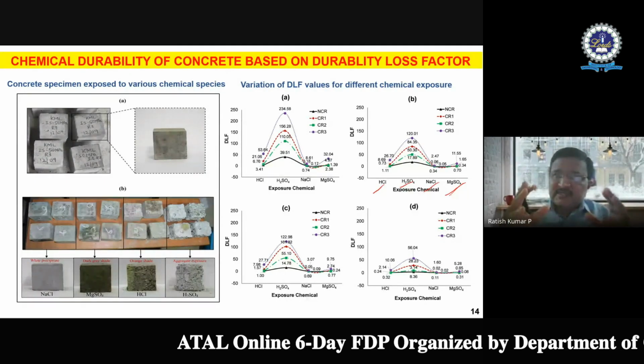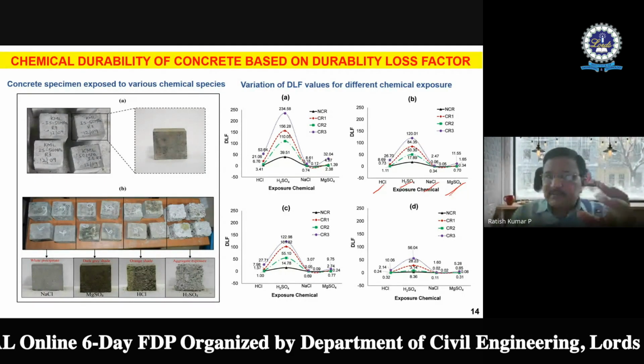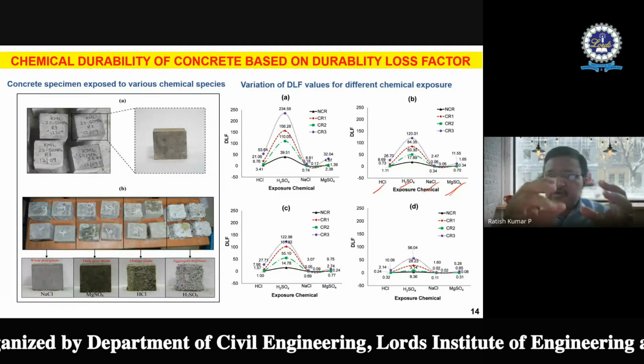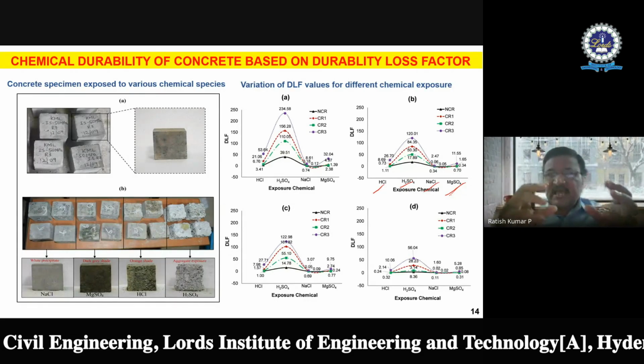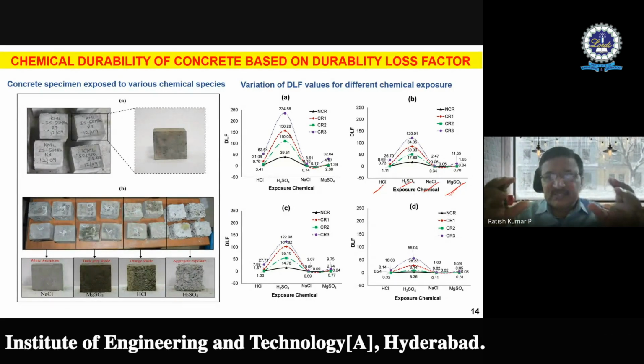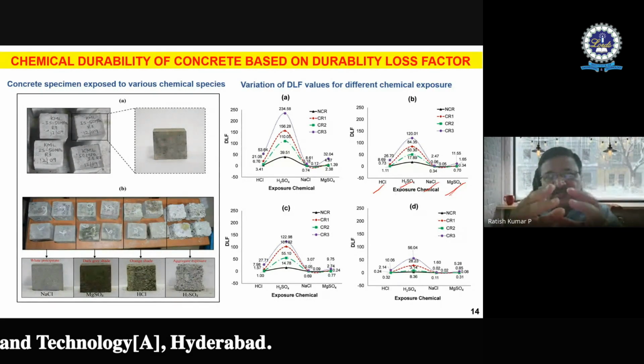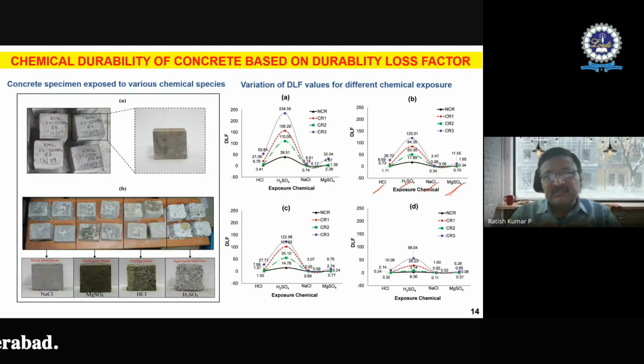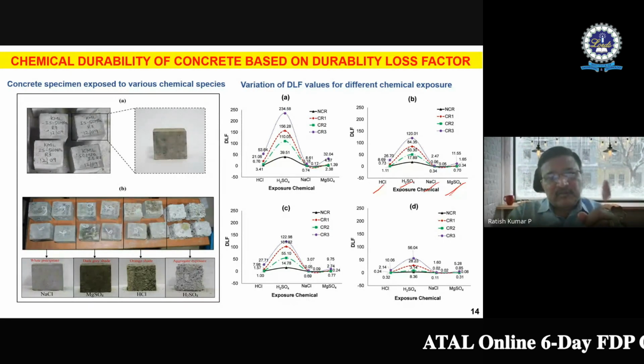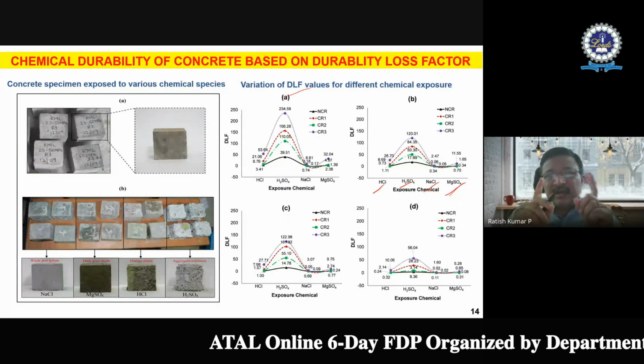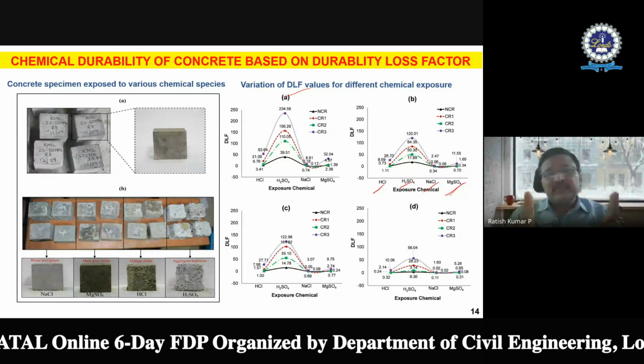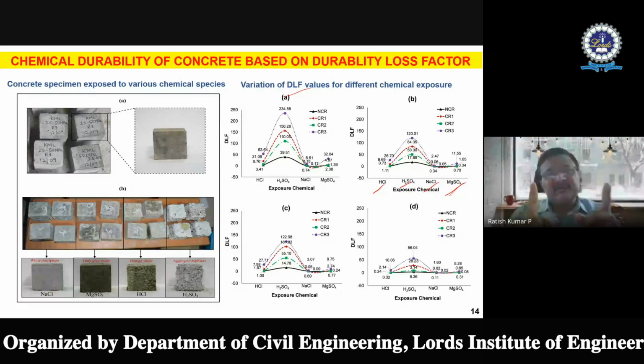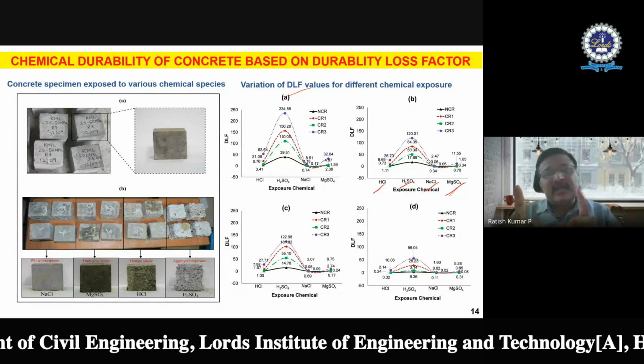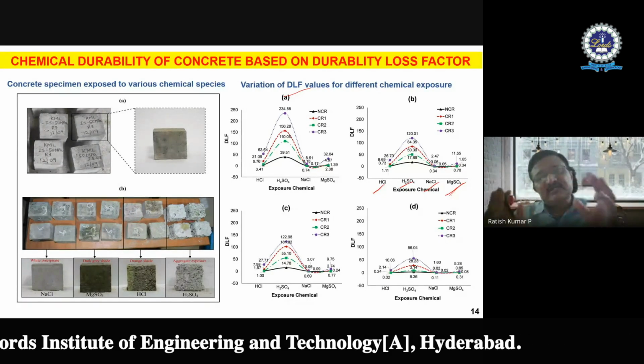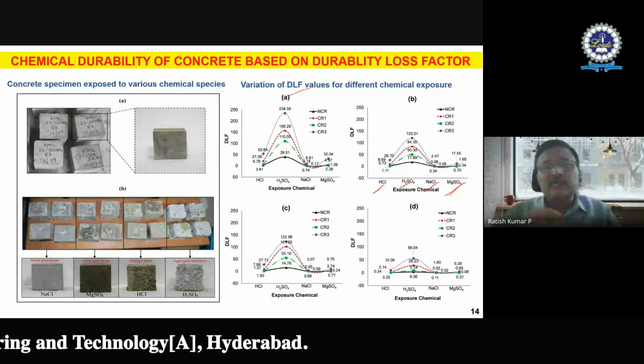So I combine these three: the acid attacking factor, which is a dimensional factor, the acid mass loss factor, which is a change in mass, and the acid strength loss factor, which is a change in strength. I combine them into a unified factor called the acid durability loss factor. The durability loss factor is equal to the mass loss factor multiplied by the strength loss factor multiplied by the attacking factor.